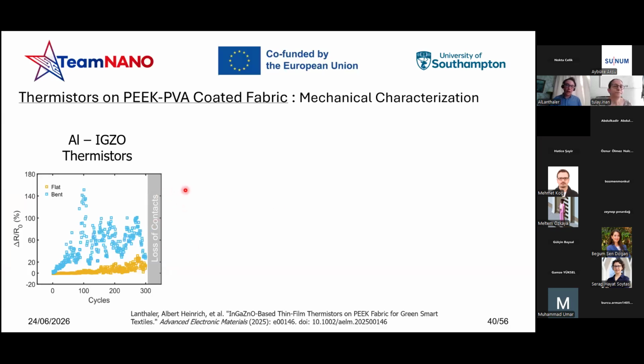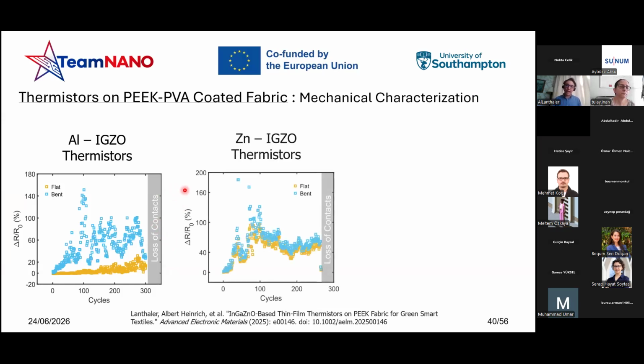As you can see here, the aim was to achieve 1,000 cycles, but unfortunately for both the aluminum and the zinc, at around 300 cycles, we encountered a loss of contact. We do believe the main cause behind it is the formation of native oxide, both for aluminum and zinc oxide. This native oxide is a very brittle layer, and of course might have played an important role in the mechanical characterization.